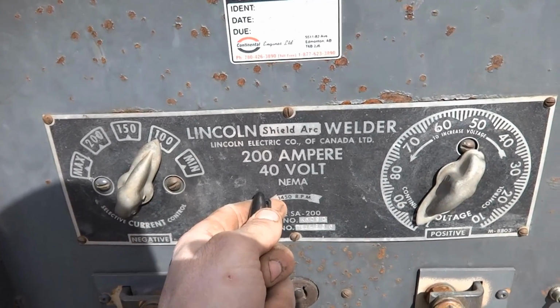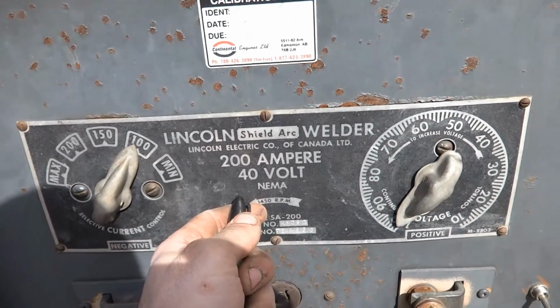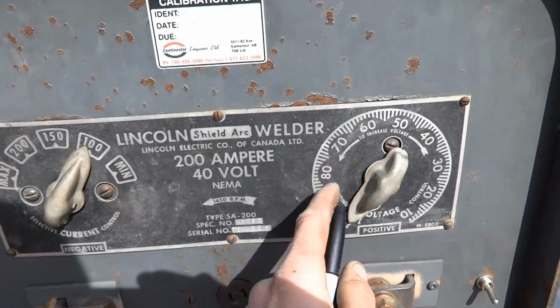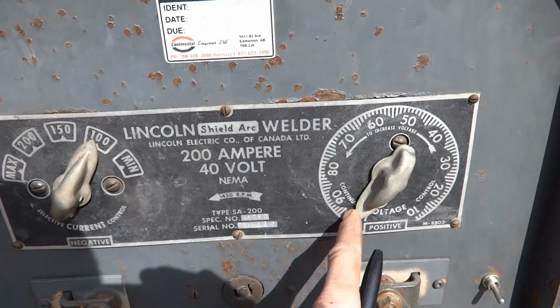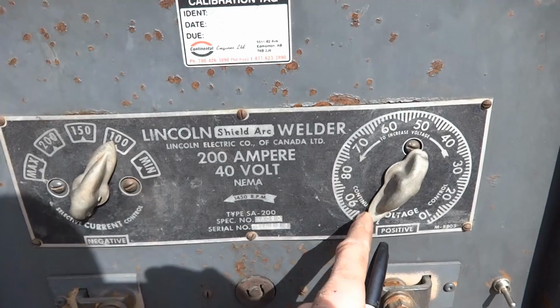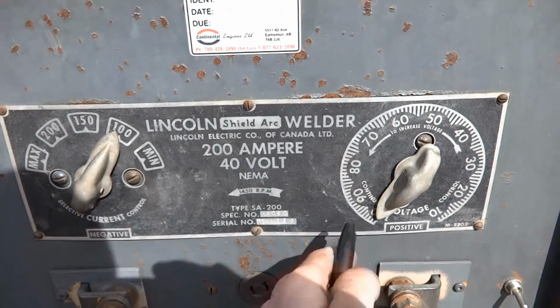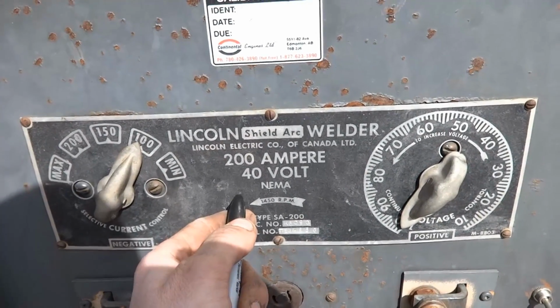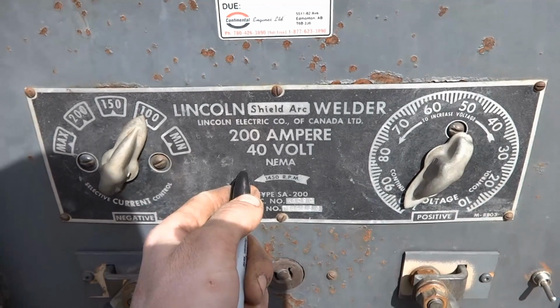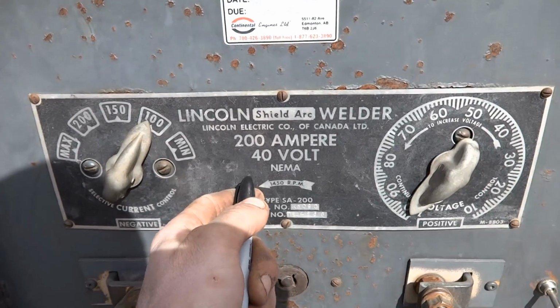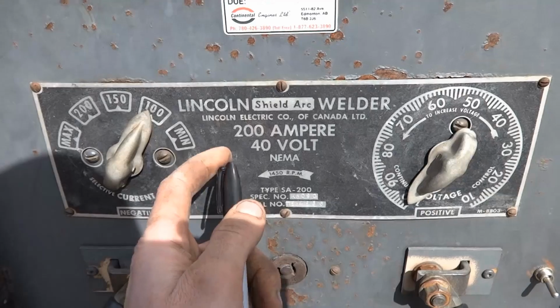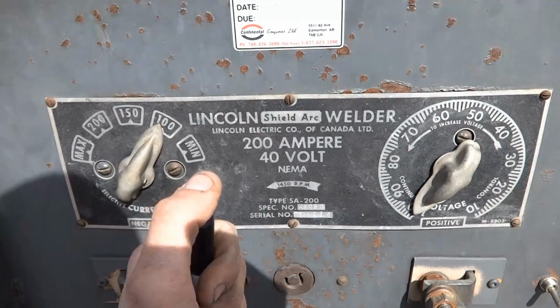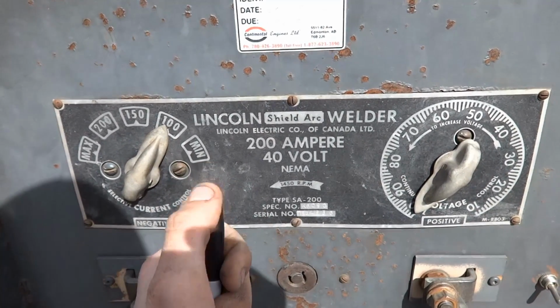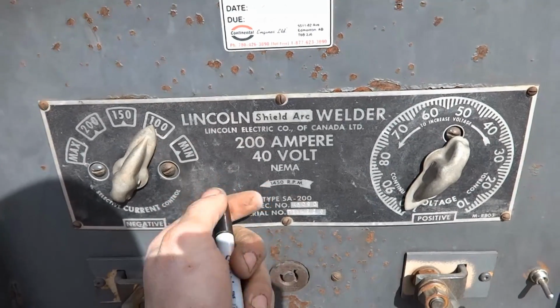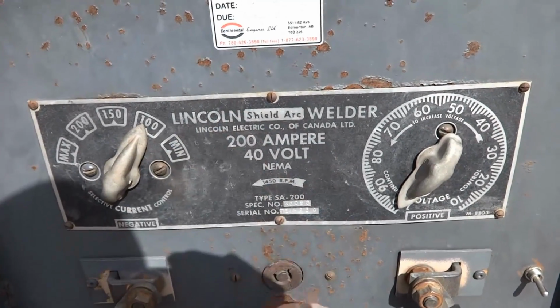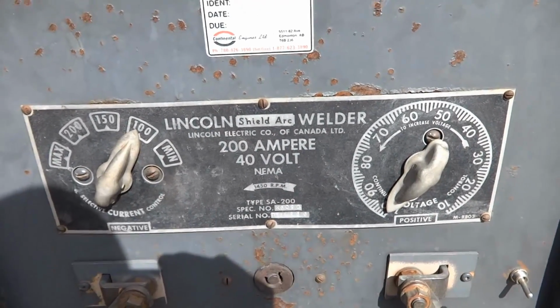So you have an increase in voltage using arc length, and you have an already volt heavy setting on your machine, so you're counterproductive. The very second you do touch the pipe, you'll snuff out. The arc will reignite. The bare tip of the electrode will be shiny, bare metal. You'll throw in porosity there and you'll keep welding because the electrode reignites. That's why you get porosity.